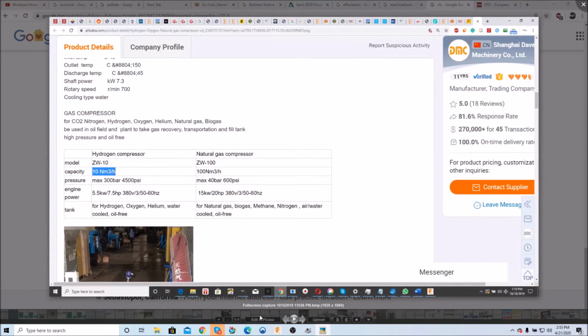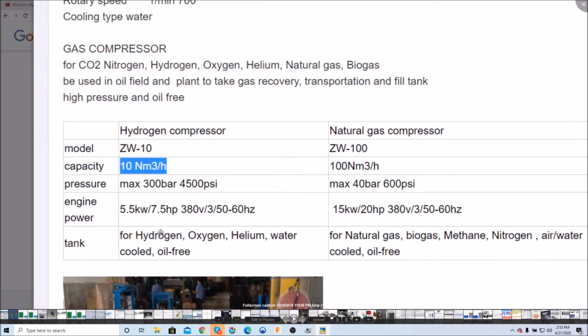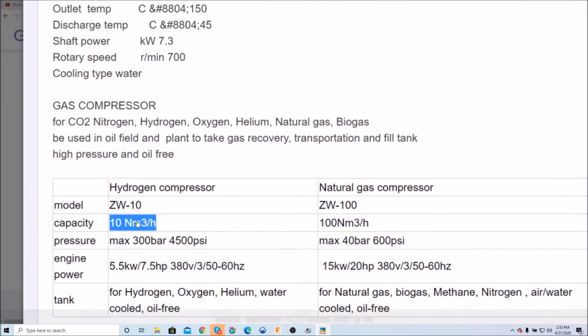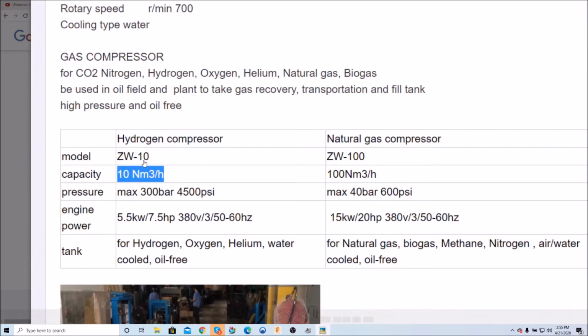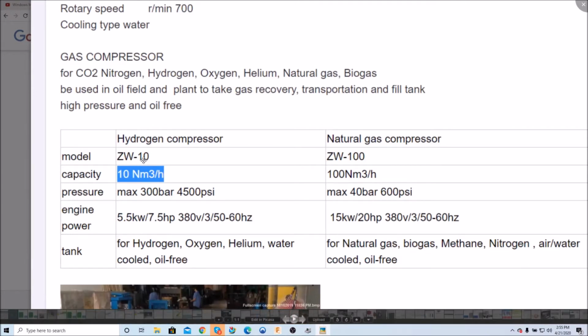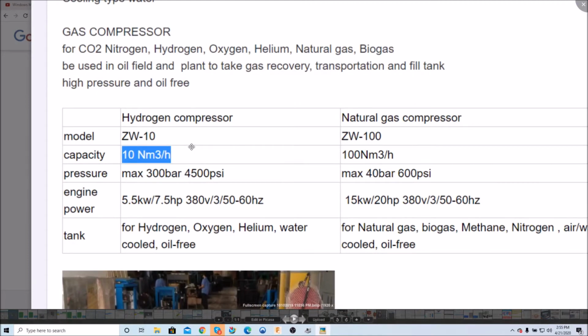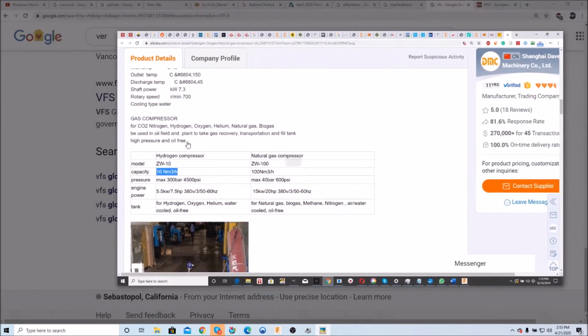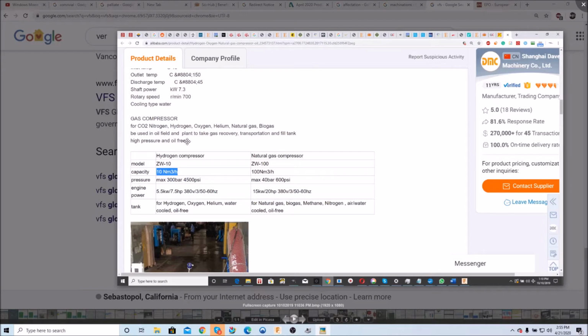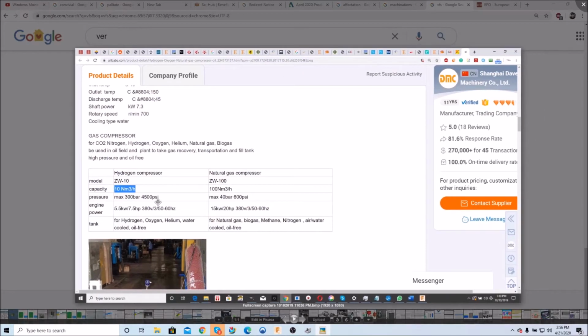Okay, so hydrogen compressors. You can see just from this number, the power consumption is very high per kilogram of hydrogen. Capacity 10 cubic meters is 0.82 kilograms. 5.5 divided by 0.8 is about 7 kilowatt hours per kilogram, and that's to 300 bar. So 700 bar, it's not double, but it's probably 50% more. So power required to compress is not linear. It's not intuitive. So at higher pressures, power consumption is reduced.